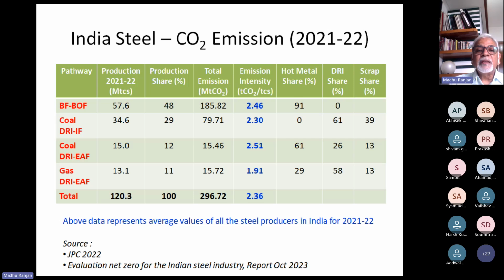Same if we want to compare with that of India, this is the all India average for the year 21-22. The blast furnace in combination with BOF for steel making has a production share of nearly half, and their emission intensity is 2.46 tons of CO2 per ton of crude steel. If we consider the DRI route made from coal, and this DRI used in induction furnaces for steel making, their emission intensity is 2.30. If the coal-based DRI is charged in an electric arc furnace, the emission rate goes up to 2.51, principally because this process route also consumes nearly 60% of hot metal from the blast furnaces. So the contribution of CO2 from the blast furnace is added up here.